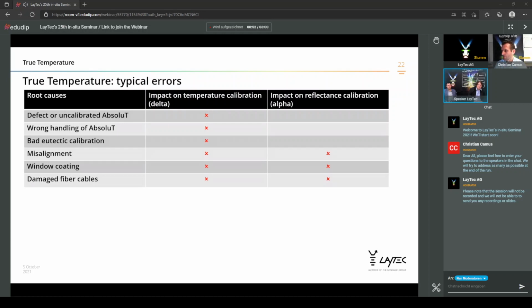We've seen effects that when the process vacuum pump is kicking in at maximum pumping performance at low pressures with a high gas flow, even slight vibrations on the system, which definitely do not affect the growth process, can affect the transmissivity and show a change in the amount of light that's transmitted through the fiber cables. We'll see some plots about this effect later on.